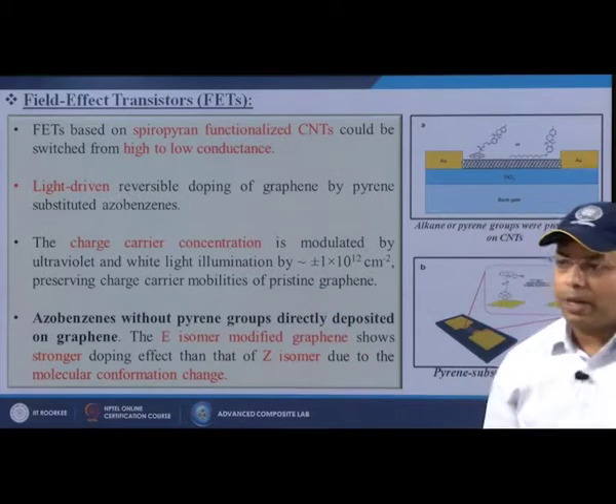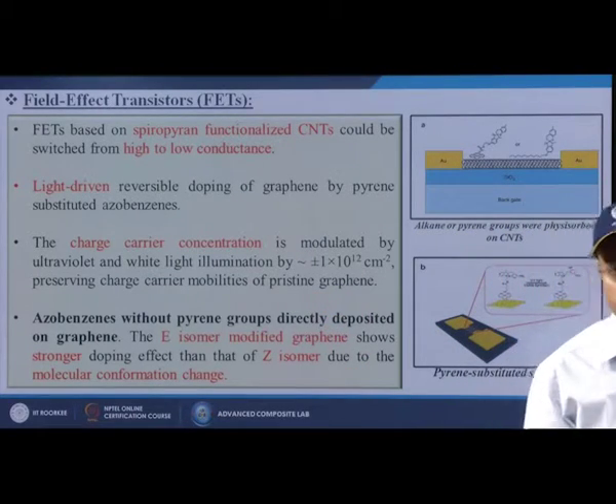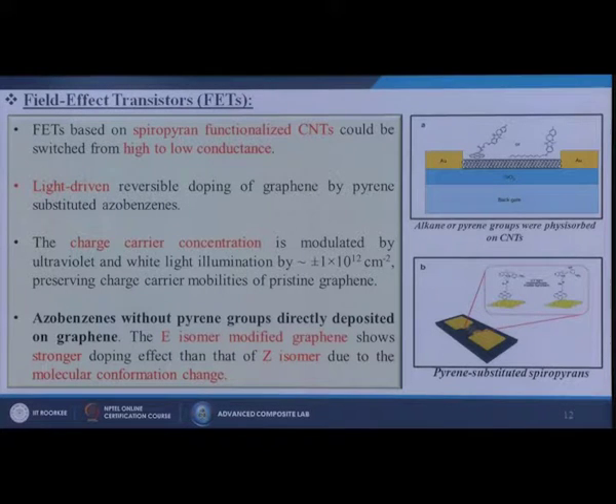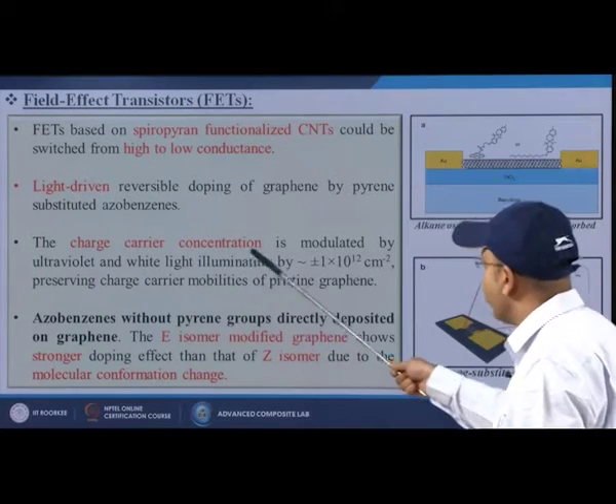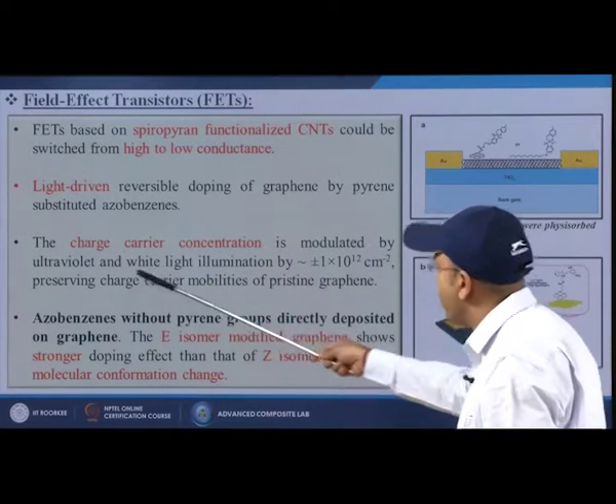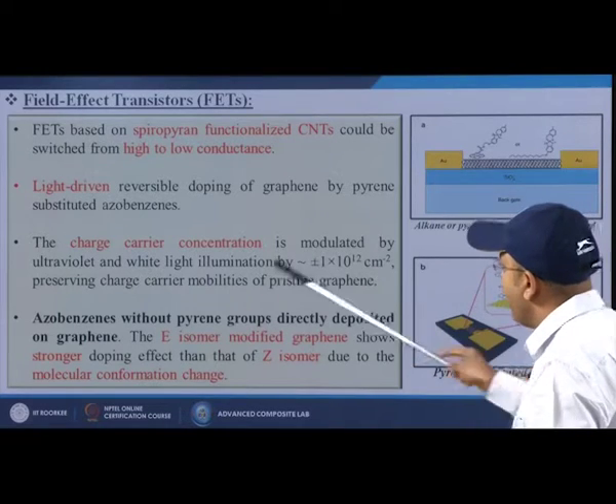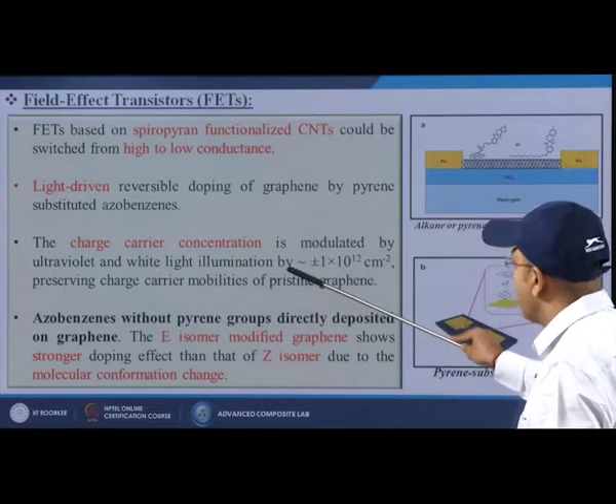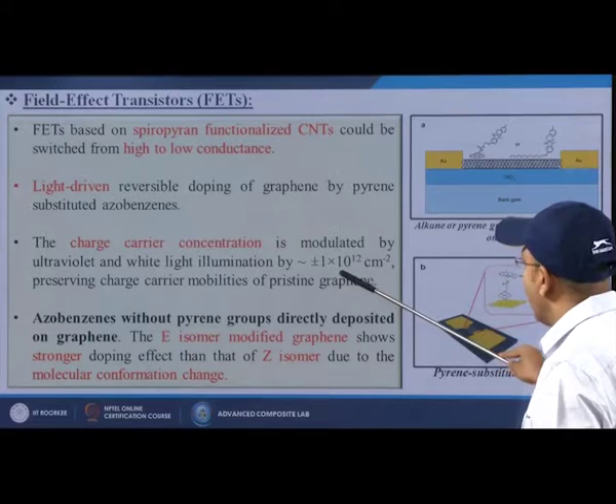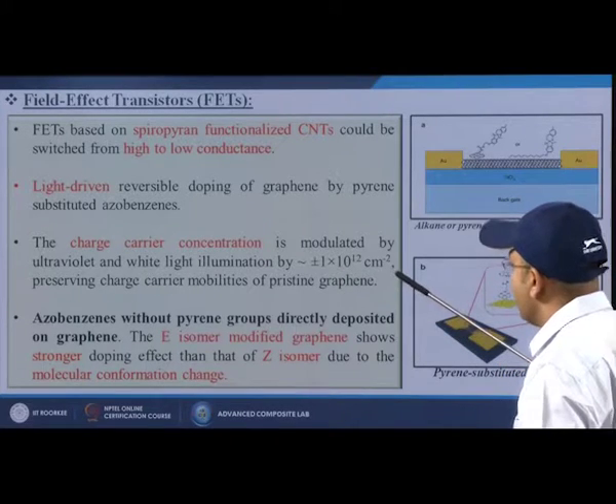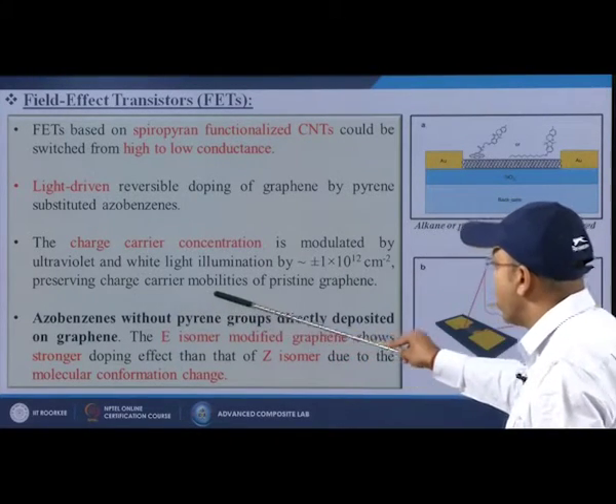So by doing this kind of modifications, or maybe functionalizations, we can enhance the electrical properties of that particular material. Not only that, the charge carrier concentration, which is the vital parameter for the FETs, is modulated by ultraviolet and white light illuminations by plus minus 1 times 10 to the power 12 per centimeter square, preserving charge carrier mobilities